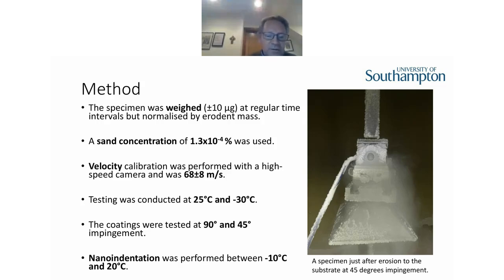And we did the tests at two angles, primarily. For polymers, you'd expect the lower angle to give you slightly higher erosion than you get at 90 degrees. The other way around, if the surface is brittle, you get more erosion at 90 than you do at 45.